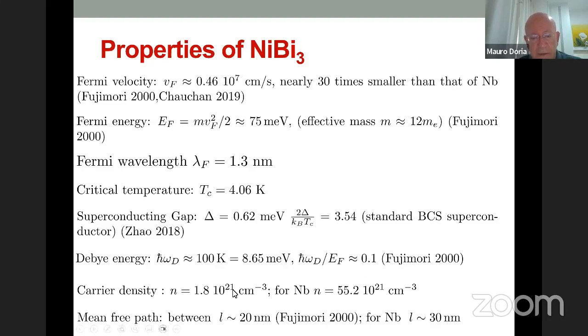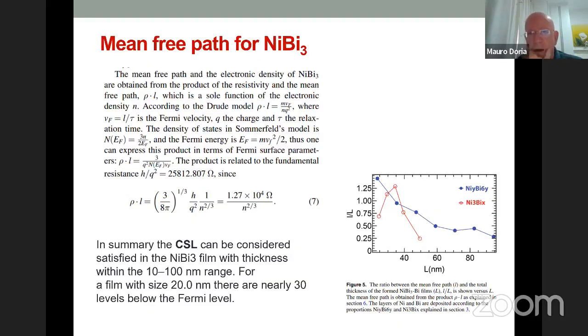The carrier density is smaller than niobium, but it's okay, 55 to 1.8. The mean free path was determined to be 20 nanometers and so forth. Okay. So what's the mean free path for niobium bismuth 3? So here's the formula. This is the Drude model formula. If you multiply rho times L, you obtain the fundamental resistivity, e squared over h, a factor here, and then the density here. So it does not depend on temperature, it does not depend on collision.